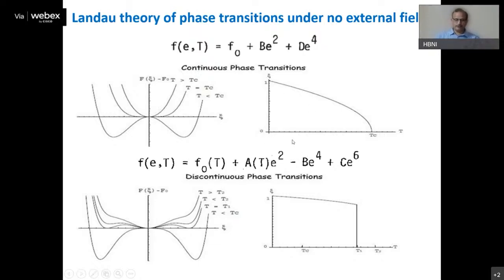Now, Devonshire included one more term, the sixth power of this order parameter, in order to describe discontinuous phase transitions, or by Ehrenfest criteria, first order phase transitions. In this case, the order parameter has zero value up to a certain temperature, and there is a discontinuous change in the value of the order parameter at some temperature, below which it increases with some systematics. To show that this order parameter arises discontinuously, we can see in this plot that there are two characteristic temperatures, called spinodal temperatures. One temperature corresponds to the inflection point for the daughter phase, and the other corresponds to the inflection point of the parent phase when the daughter phase becomes the more stable phase.